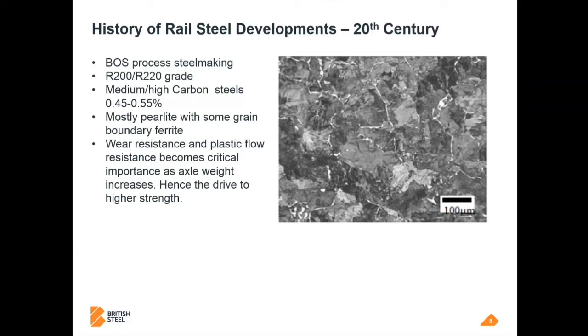Here you can see the microstructure. Now the dominant phase has become pearlite, and you just have some grain boundary ferrite, just diffuse and maybe a continuous network, but it's a minimal part of the microstructure. Again, what you see from just adding more carbon is that you get the increased strength, the increased hardness. Toughness is less important in rail steels. Even modern rail steels, you would not call them ductile, but they're not designed to be. They're always in compression in service. They're always under heavy axle weight on a small contact patch. The material science needs to focus on the contact energy and resisting that.